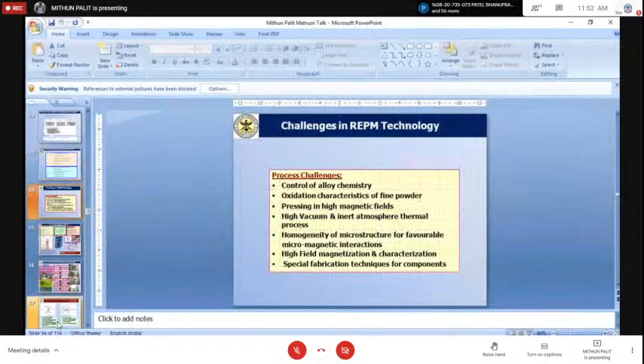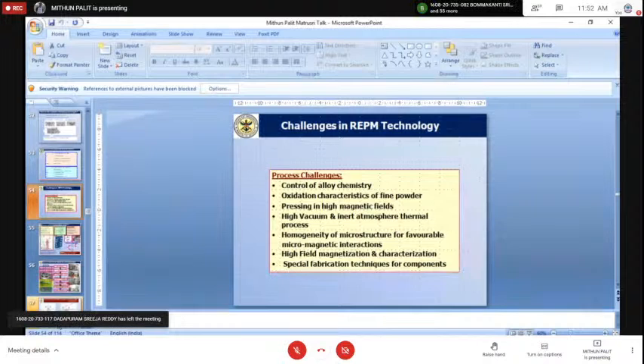So when we talk about the rare earth permanent magnet, there are several challenging things, because of controlling the chemistry; rare earths are very reactive with the atmosphere. So we have to process under inert atmosphere, and that too we are handling powder metallurgically fine particles. And then we have to apply a high amount of magnetic field, because as I told, they are anisotropic, so they need a higher magnetic field to flip their domains into the desired direction. So therefore you need a very high magnetic field.